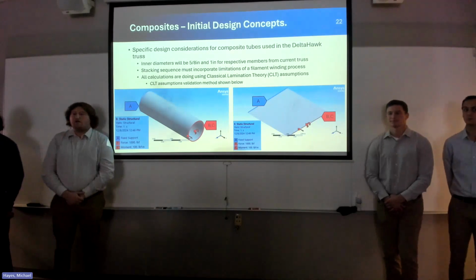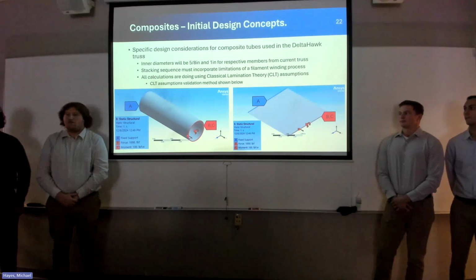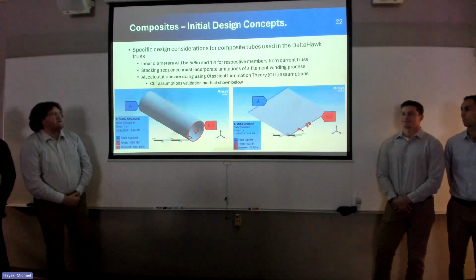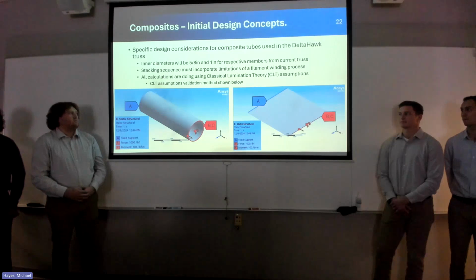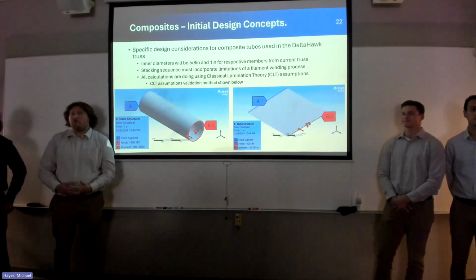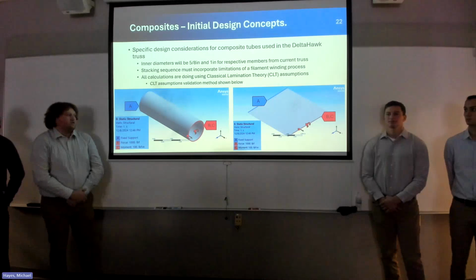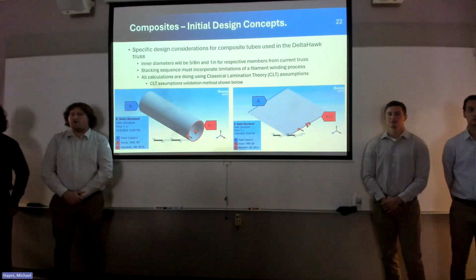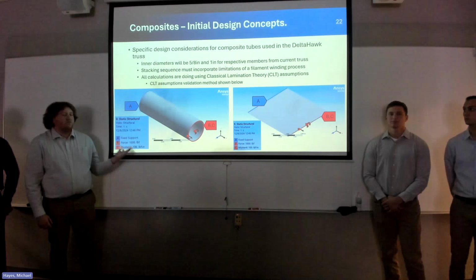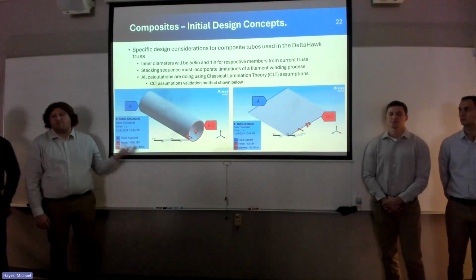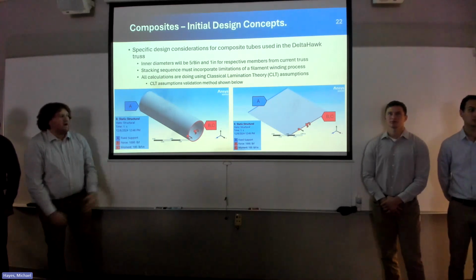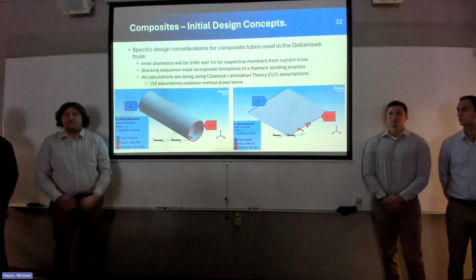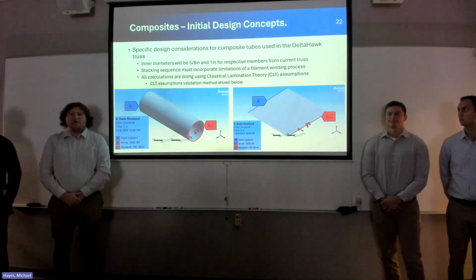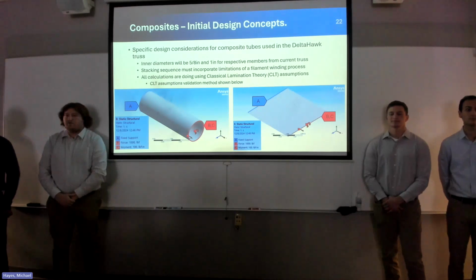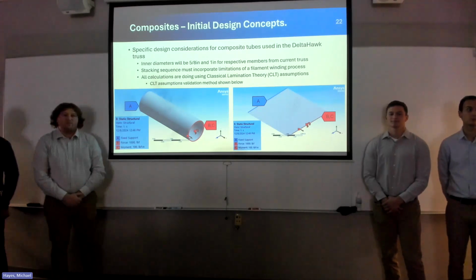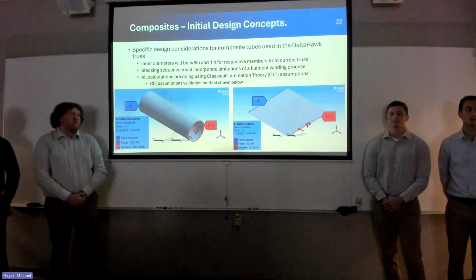And then all the calculations that I did by hand in this project use the assumptions of classical lamination theory. Since the composite needs to be a thin laminate for that assumption, we have to assume that we are unrolling our tube into a flat plate. To show that this is an okay assumption to make, I did a quick ACP validation. I made a composite tube with the same stacking sequence, same boundary conditions, and the same dimensions as the plate that I mentioned earlier. By that I mean the circumference of the circle is the same width as the plate. The analysis produced an 85% difference in the strain in the fiber directions, which is quite a high percent difference. It shows that this is not a great assumption to make.